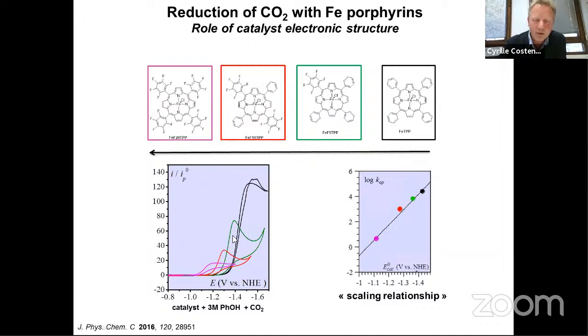Of course, by increasing the scan rate, in each case, you can reach a plateau, measure the apparent rate constant. And interestingly, if you plot this apparent overall rate constant as a function of the standard potential of the catalyst, you get a scaling relationship, which makes sense because if you stabilize iron 0, you make it less reactive toward CO2 and you decrease the apparent rate constant.